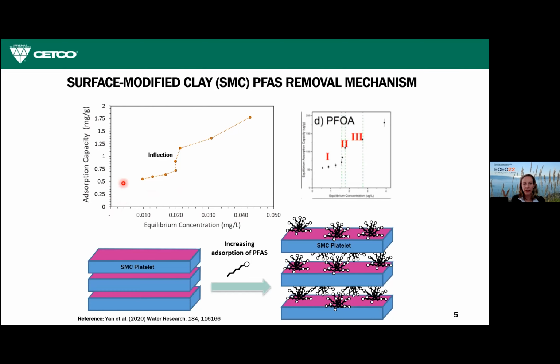And as the starting concentration increases, you get the step change in adsorption capacity. So you're getting more PFAS in per gram of Fluorosorb. And that's because, and this has been verified with modeling and also looking at the d-spacing in the laboratory, published in Water Research in the last couple of years, the d-spacing also increases as various PFAS molecules sorb to the surface modification in the clay.